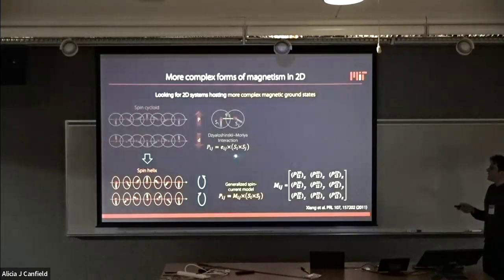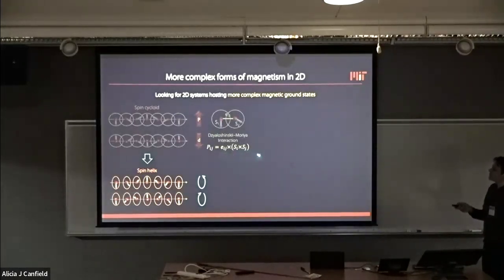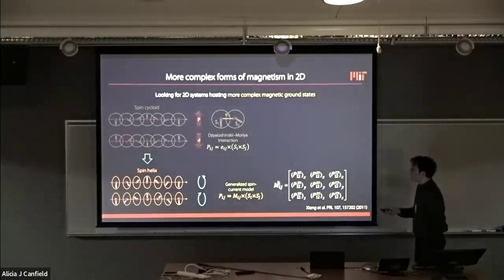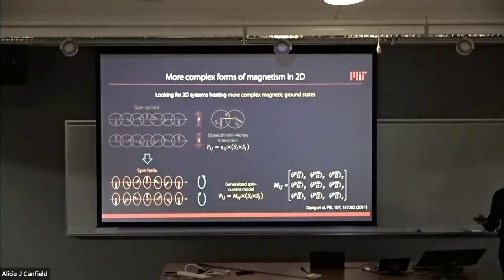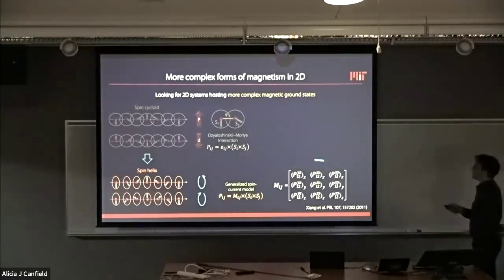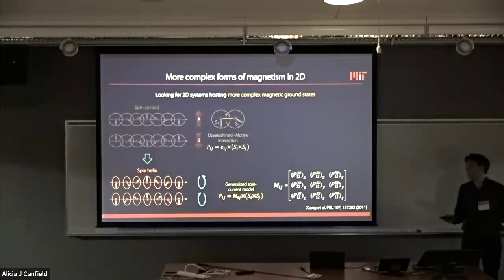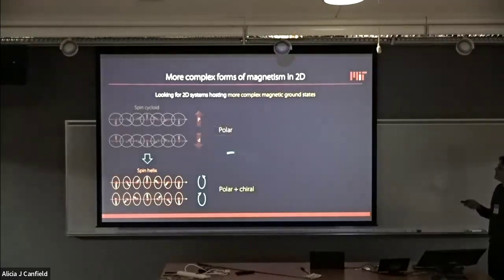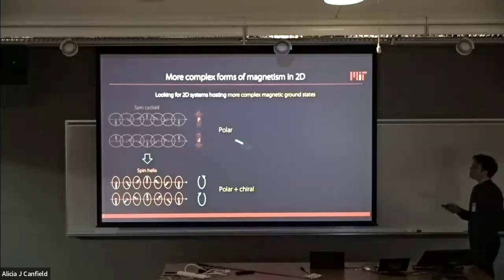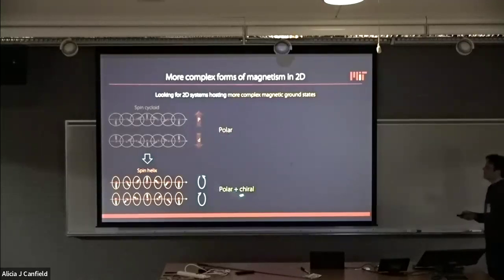So there's a rigid connection between the breaking of inversion symmetry and the handedness or the chirality of the helix. And it turns out the Dzyaloshinskii-Moriya interaction doesn't work for a helix, because the spin rotation plane is perpendicular to the propagation direction, which would be the bond axis between the two neighboring spins. But there is a more generalized spin current model, which goes beyond the Katsura-Nagaosa-Balatsky model, which has magnetoelectric tensors, which under certain conditions can allow for a polarization to arise in spin helix systems. What's exciting about these types of materials is that they have spin textures that break inversion symmetry, so they give you a polar ground state. But in the case of the helix, you also have a chiral ground state.